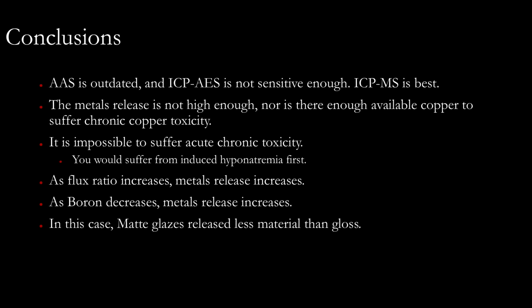Metals release is not high enough, even in our worst case scenario, to get anywhere near chronic or acute copper toxicity. It's not, in my eyes, a risk, or in the CDC's eyes, they're telling us we can handle more than that. You can't suffer acute chronic copper toxicity. You'll induce hyponatremia before you do that. Please, nobody go do that. It's not recommended. As our flux ratio increases, we notice that metals release increases as well. Puts more importance on formulating your glazes properly for the most durability you can achieve.